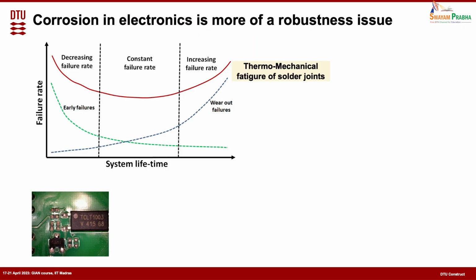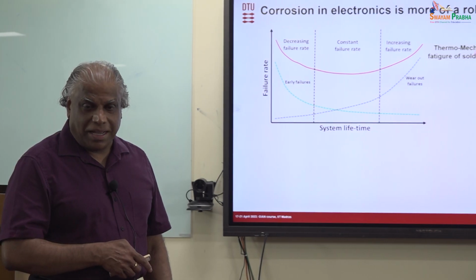That's one of the key failure modes people see in electronics, and this thermomechanical failure is a wear out failure because it takes time to happen and it can be predicted, right? So you can do many experiments in the lab and make a model for the thermomechanical fatigue, and we can predict that this joint can work for 10 years. This is what electronics and power electronics people do, and with the models they have, they predict it will take at least 15 years for these things to happen. Do you think that our corrosion failure will fit into that?